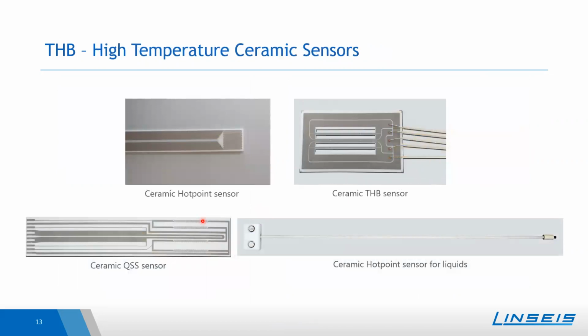On this slide, you see the ceramic version of all of these sensors. So for the THB version, we have a ceramic version, as well as for the high conductive materials, the QSS sensor. And the hot point sensor is divided into two groups, one for solids and one especially for liquids, powders, and pastas. These ceramic-based sensors allow the measurement up to 700 degrees, but one needs to keep in mind that the accuracy of the ceramic-based sensors is slightly lower compared to the Kapton foil sensors, as here the substrate is rather thick compared to the Kapton foil, and one cannot exclude the thermal conductivity of the ceramics, so that here the accuracy is slightly lower.